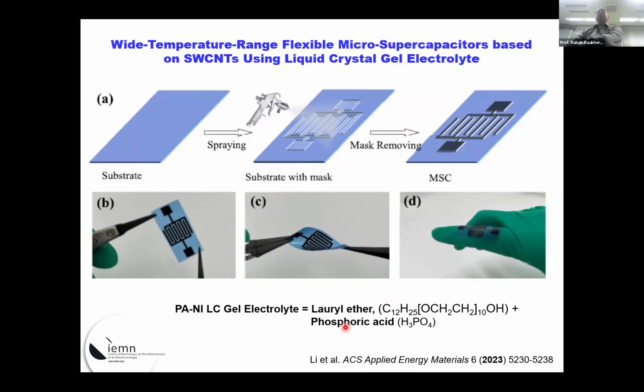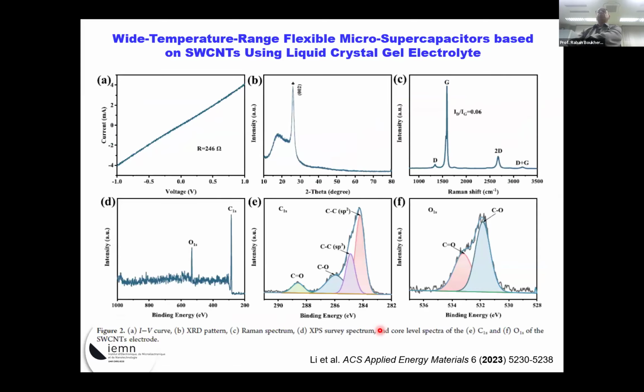Here we applied a gel electrolyte based on lauryl ether and phosphoric acid. It's like a liquid crystal. Now if you look at the characterization, we looked at the conductivity of the single-wall carbon nanotubes when you spray them on the substrate. It's quite good. You can look at the XRD as well, and you find the features of single-wall carbon nanotubes. The same applies in the Raman. You have essentially the G band, but also some defects, fortunately, because you operate in air. Some of these carbon edges are oxidized, so you generate some defects. You can see it also by the presence of oxygen in the XPS. But essentially on the carbon you see sp2 carbon. Some of the carbon is oxidized on the surface, or it could also be from some contamination.